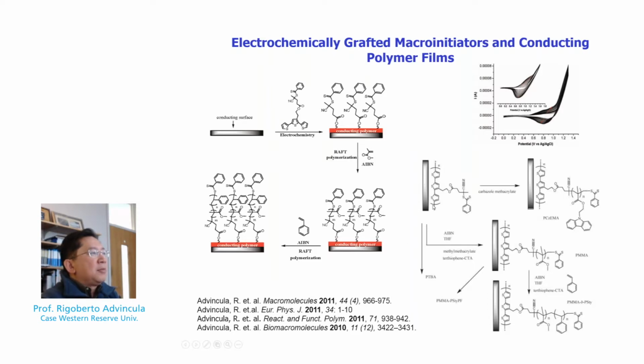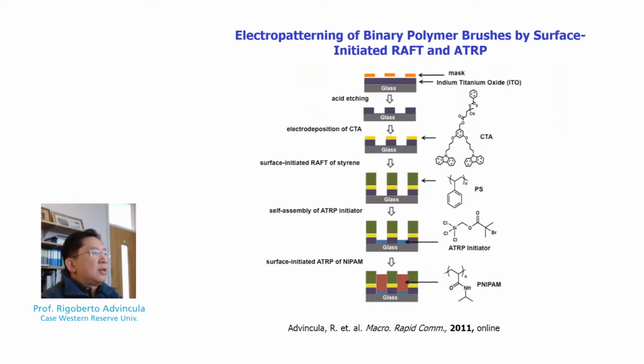We published several papers that demonstrated that the conducting polymer macro initiator can be grafted by cyclic voltammetry. In fact, this can be done selectively as a patterned layer. Here we have a patterned surface where the conducting layer can be modified by this bifunctional electropolymerizable carbazole with a chain transfer agent. We can grow one polymer brush of polystyrene on this conducting layer.